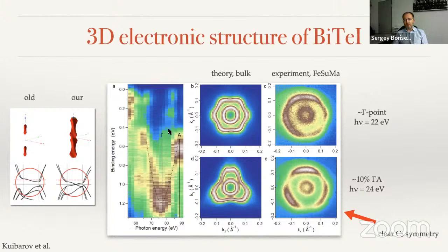So we are sensitive to the bulk and we see how the bands disperse. We identify the gamma point in a potential. And now we take the data with the photon energy at the gamma point, so 22 eV. What we see is exact correspondence with the hexagonal shape, what theory predicts. And this is normal at the gamma point.